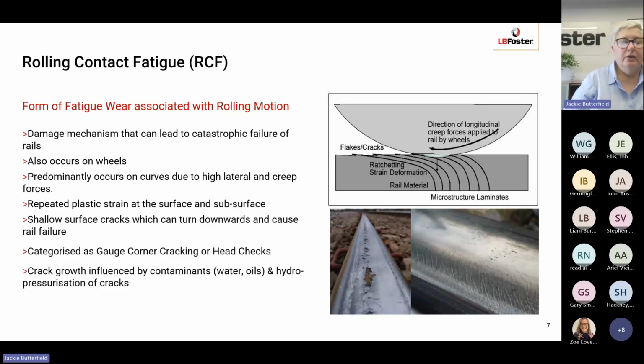Now, rolling contact fatigue can also be influenced by contaminants in the wheel-rail interface, particularly water and oils and other chemicals. And what happens here is the water will, through capillary action, seep into the cracks and pressurize or hydropressurize the cracks and open them further. So the phase of crack growth which leads to the turn down of the cracks down through the rail head is often associated with hydropressurization.